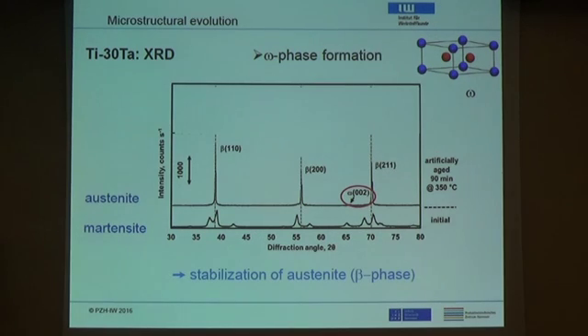It's fully austenitic then. And the reason why it's fully austenitic is because you form the omega phase, which is shown up here. The omega phase is really hard to see in X-ray. You see this tiny little extra peak. This is what stabilizes the austenite and what kills your material.